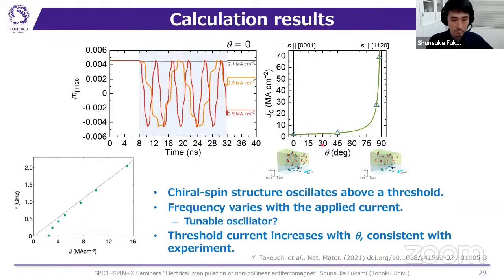And also, we calculated this behavior as a function of the angle between the current and the Kagome lattice. 0 degrees means that the accumulated spin is perpendicular to the Kagome lattice, and 90 degrees means that the accumulated spin is in the Kagome planes. As you can see, the threshold current density increases when the angle increases to 90 degrees. This is also consistent with the experimental results.